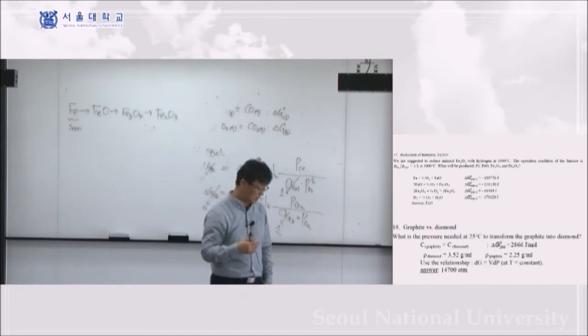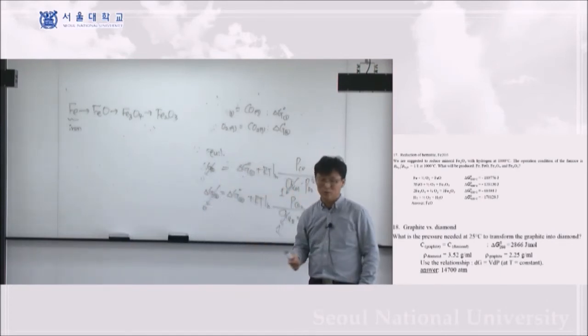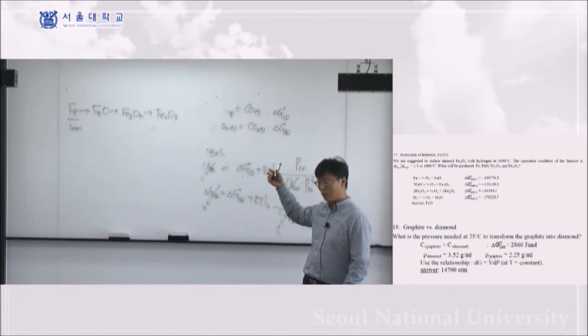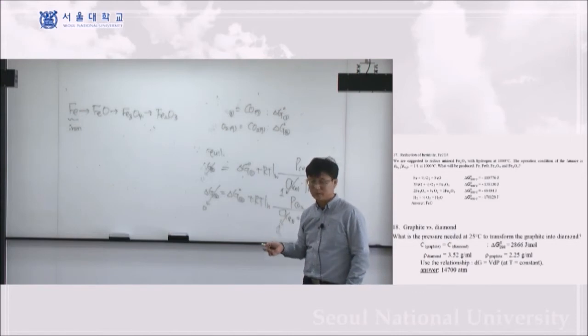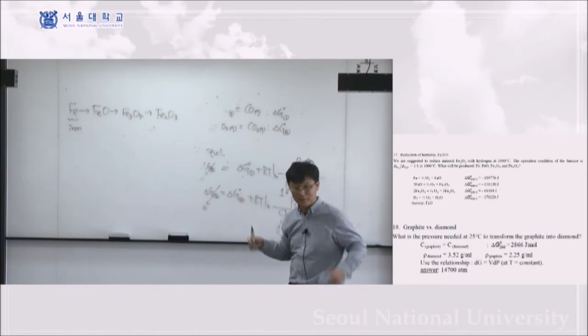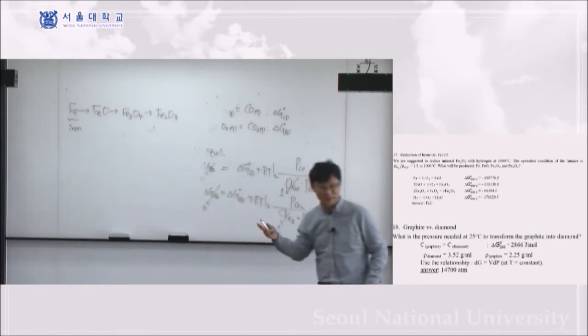So typically in terms of the iron and steel making process, when you first produce the iron by the iron ore reduction by the carbon or CO gas, it will produce the liquid iron containing about 4 or 5% of the carbon. That we typically call iron or pig iron, P-I-G, the animal, pig iron. I don't know whether you heard about this one or not, but we call it pig iron.